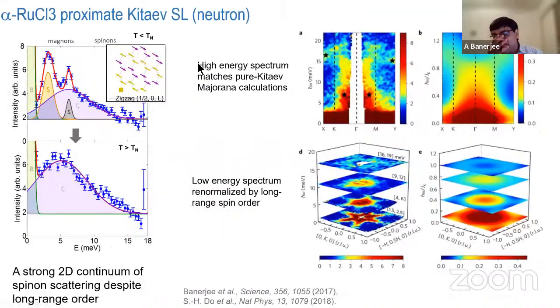But let's go back to the neutron scattering results. These are some of the neutron scattering results that we published. What we find is that if you look at the intensity as a function of energy at the gamma point, at low energies and low temperatures, you get these sharp modes sitting on top of a broad continuum of scattering. And these are the broad modes that we are in search for. As you see, this doesn't look like a paramagnet. If this was a paramagnet, this would have been just a Lorentzian centered at 0. That's not what you get. What you get looks different.